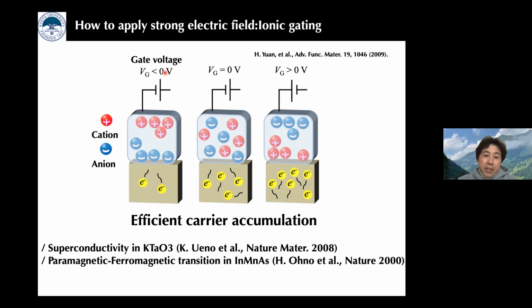When we apply a negative gate voltage, the opposite situation takes place. So by using this technique, we can freely and automatically control the carrier type that is accumulated on the top surface of the solid. This ionic gating technique is a very promising way to control physical properties. In fact, superconductivity in potassium tantalate was first observed using this technique, and a paramagnetic-ferromagnetic transition in indium manganese arsenide was also realized using this technique.